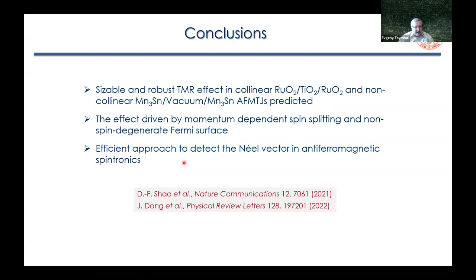So this band is present for upspin electrons and isn't present for downspin electrons. This selectivity in the k-space is basically responsible for the giant tunneling magnetoresistance effect in this kind of tunnel junctions. So my argument is, if it's possible for ferromagnetic tunnel junctions, it would also be possible for antiferromagnetic tunnel junctions. But again, I emphasize that the major difference here is this critical and important condition: you really need conservation of the transverse momentum, because if you don't have it, then you allow channels where you flip the spin.